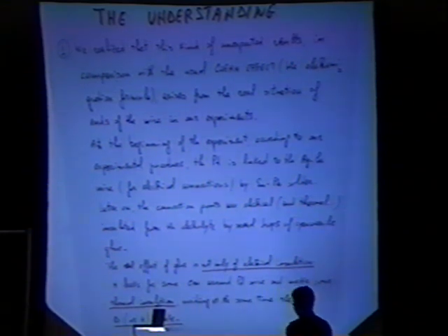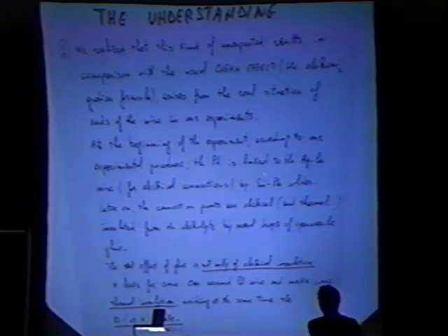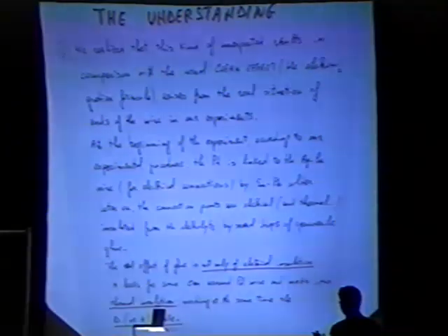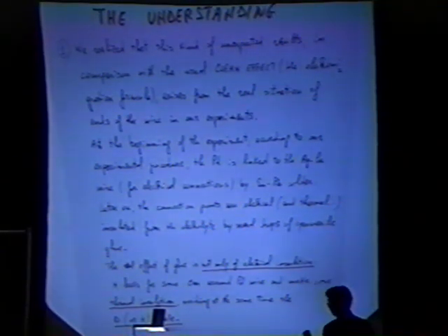So we try to understand what really happened, what is a very strange phenomenon. We realized that there was some effect due to our mechanical construction of the system, how to solder the wire. We soldered a thin conventional palladium wire with the copper wire and made some glue to insulate, and so on. And we found that how we make this arrangement of the cell, the preparation, has some effect on the final loading.